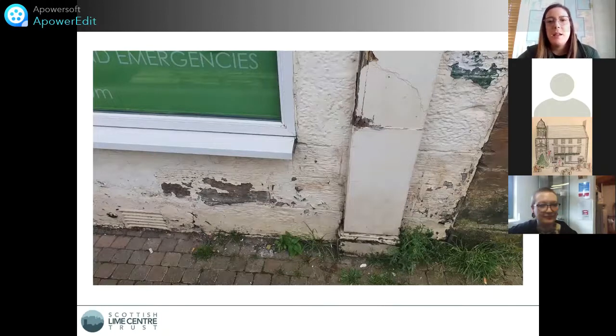So while paint technology has progressed to allow more UV resistant paints, older masonry paints are susceptible to UV degradation. As you can see in this picture, there's quite a lot of flaking, and it's become brittle and cracked over time. And again, this will be allowing a lot of water in, but generally not really allowing a lot of water evaporation, so not allowing the stone to dry back out again. And you can see it's not only perished on the stone, but it's actually perished on the timber pilaster as well. So it is likely all decorative coatings will require a topping up or completely renewing, especially when adjacent to a busy pavement or roads, because of the frequent wetting and salt attack.